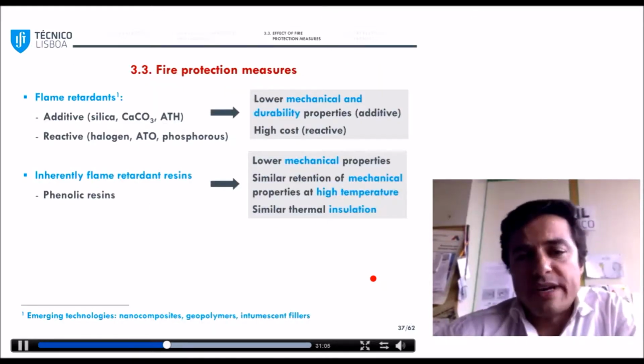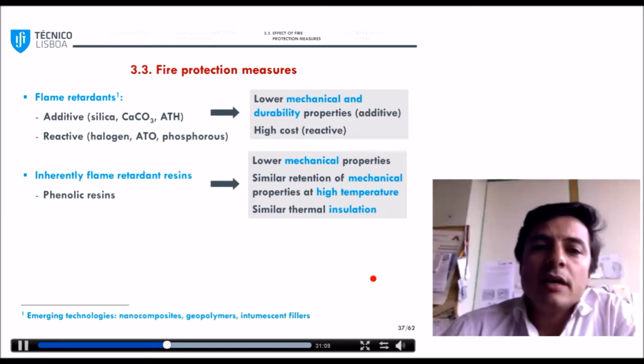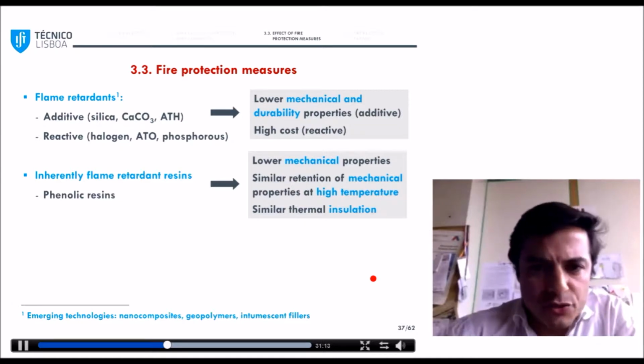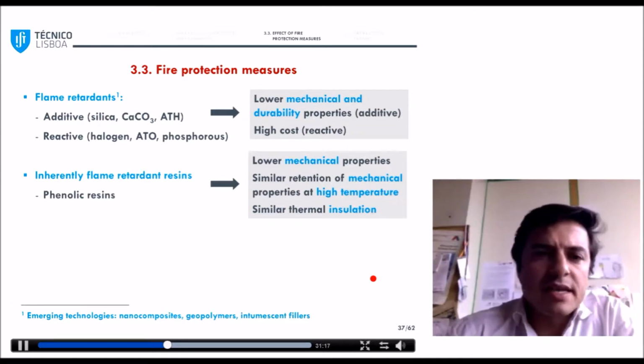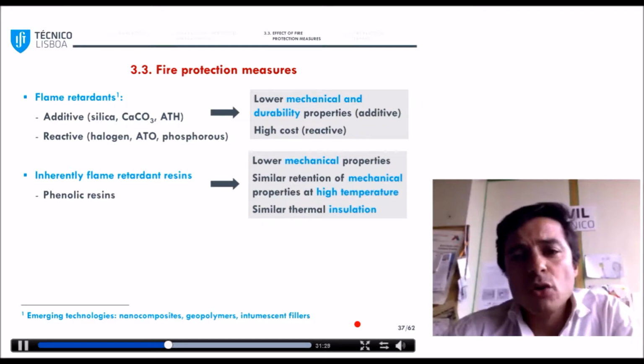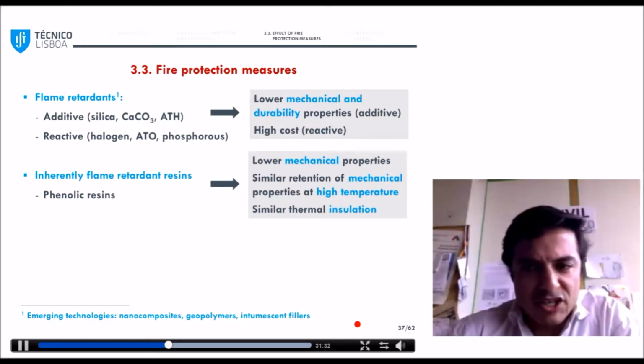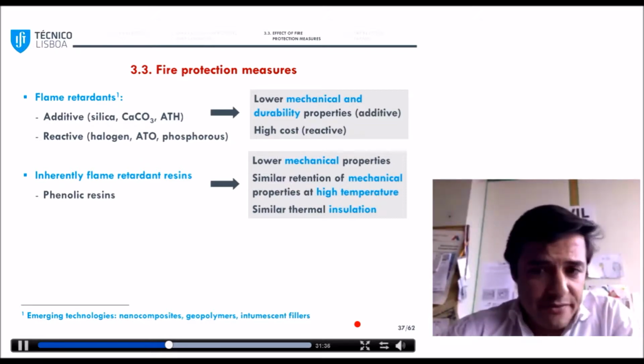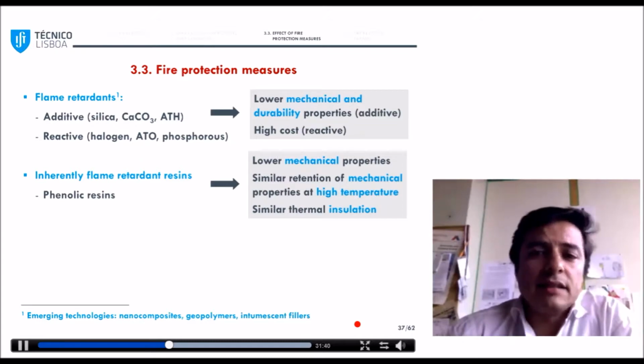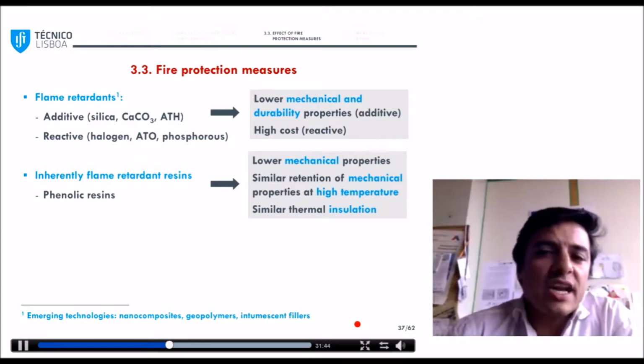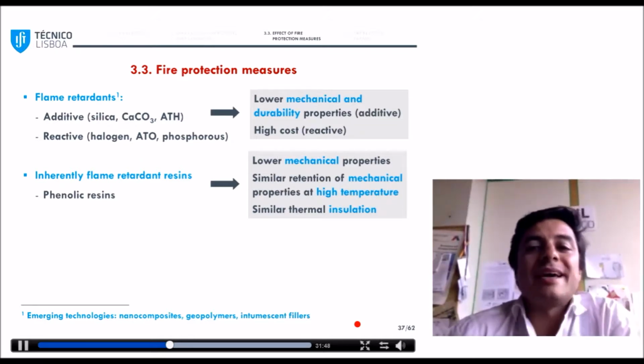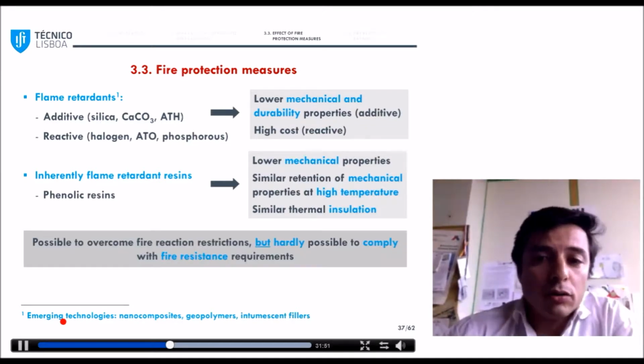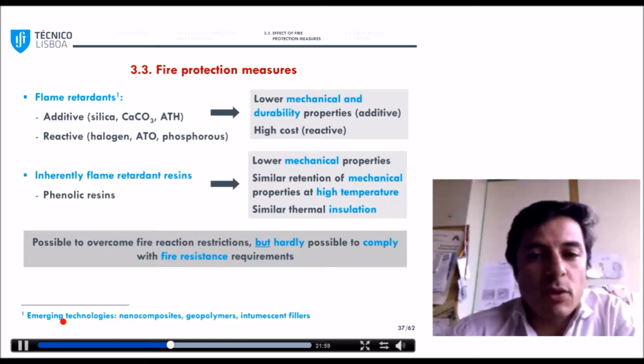Now, to improve this poor fire reaction performance of GFRP, two basic approaches have been followed in different industries. The first has to do with the use of flame retardants, which can be added to the base resin and eventually react with it, and the use of inherently flame retardant resins, that is, phenolics. So both approaches significantly improve the fire reaction performance of the material. However, they may affect the mechanical and durability properties, and more importantly, for structural applications, they generally do not improve the mechanical performance of the material at high temperature. And therefore, although being effective in terms of fire reaction, they are not really helpful in fulfilling fire resistance requirements.